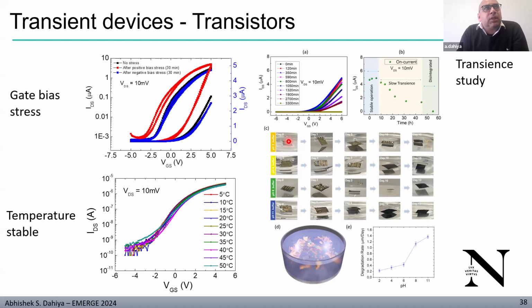The UV source we have is a commercial one. It's a 365 nanometer UV wavelength. It's a standard UV lamp we purchased, and then we calibrated it using commercial photo sensors we have purchased, and we calibrated with the distance. Degradation of substrates, I'm not sure. I have read, or we have even done it for polyimide. Mainly we are using Kapton or polyimide substrates. I cannot answer if the substrates are degrading, or at what rate of degradation. No, I cannot answer this one.